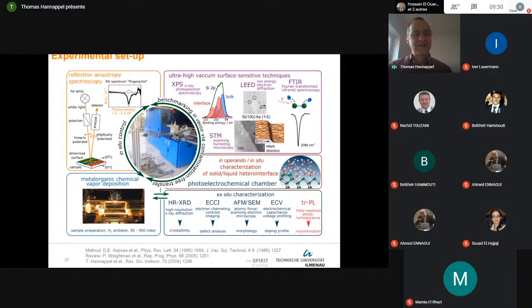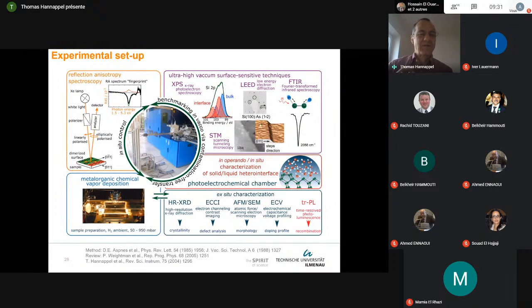On the other hand, it's a difficult tool, since the signals are not intuitively understandable. What you are more or less doing is measuring the difference of the reflectance of polarized light with regard to two different crystal axes. Not easy to understand and a little awkward. However, it rewards afterwards, since you can really follow changes of the surface in situ. This means you can see time-dependent changes during preparation or during the use of these surfaces when you are doing this optical spectroscopy.